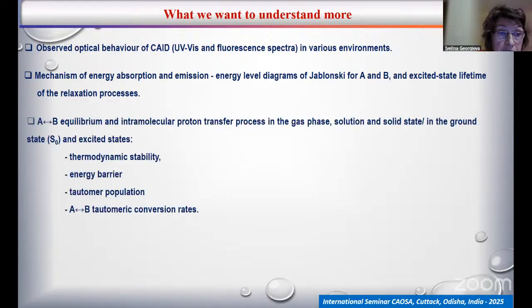the relaxation processes, and we'd like to estimate the equilibrium between these two tautomers, whose conversion is due to the intramolecular proton transfer process in gas phase, solution, and solid state, especially in ground state and including excited state. For that purpose, we need to evaluate the thermodynamic stability of these tautomers to estimate the energy barrier of the tautomer conversion, how tautomers populate depending on the condition and environment, and what the tautomeric conversion rates are.